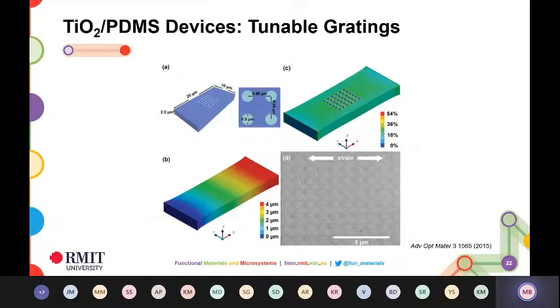We also did some finite element modeling in this case because we were trying to understand how you're able to go up to around 18 or sometimes even up to 25% of strain and not have any impact on the oxide material. So what you see in this case is the titanium dioxides are being modeled sitting in the PDMS platform. And when you apply strain, all the strain is actually absorbed by this PDMS layer. So you don't see the titanium dioxide; it is almost mechanically invisible. And that kind of explains why you're able to apply this much strain on these gratings and get away with it every single time. So the titanium dioxide sits in the middle of the PDMS, which absorbs all the strain being applied, and you're able to use these gratings again and again.